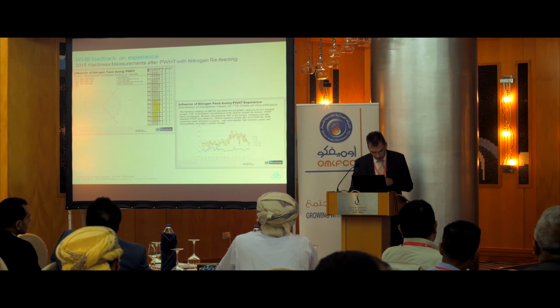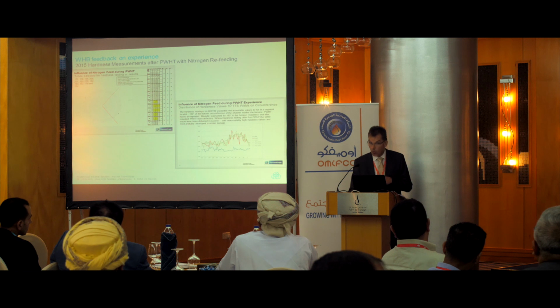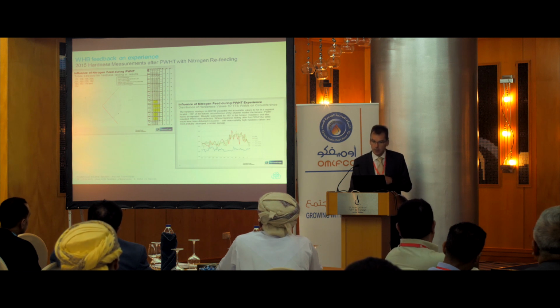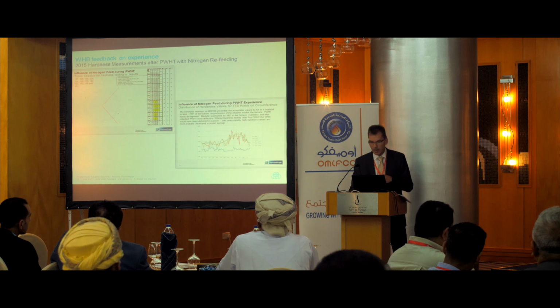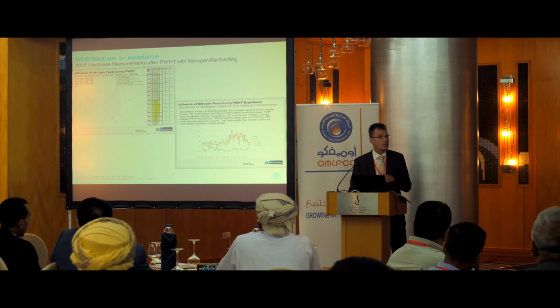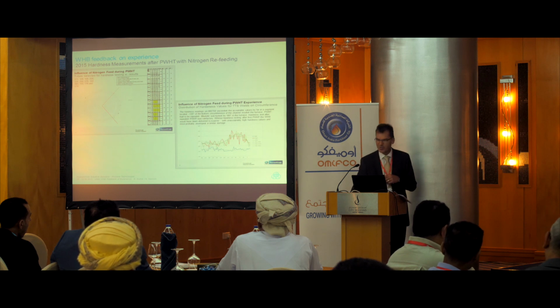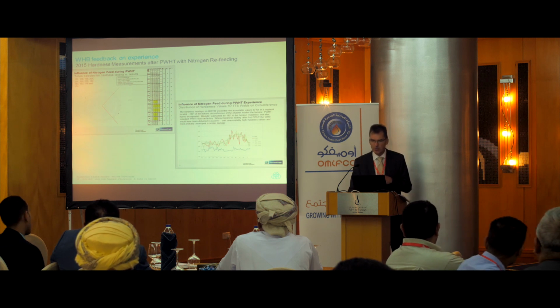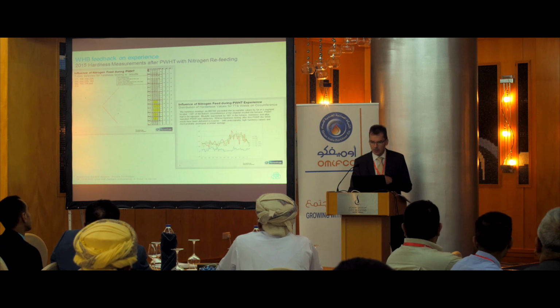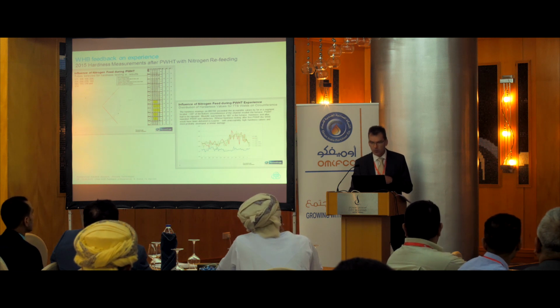But moreover, waste heat boiler 1 was of course also heat treated, with no cracks in the auxiliary shell, but again, we measured the hardness to counter-check it and found again higher hardness values. The question was now, what happened during post-weld heat treatment? Why do we have high hardness values in this other waste heat boiler where we have not fed in cold nitrogen during post-weld heat treatment?